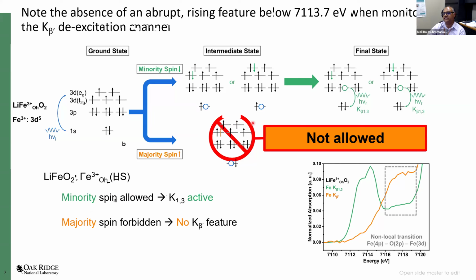So essentially in this case, the minority spin state, that is a state which the spin that you have pumped up is opposite to what exists here, which is through the K-beta 1,3 is active, while the majority spin state is inactive. So there is no K-beta prime feature. And this can be seen by changing the incident energy and monitoring the X-ray fluorescence, the X-ray emission that comes out. So we can see a good strong feature here for the pre-edge in the K-beta 1,3, but there is no feature around here. There is no sharp rising feature around here for the K-beta prime.